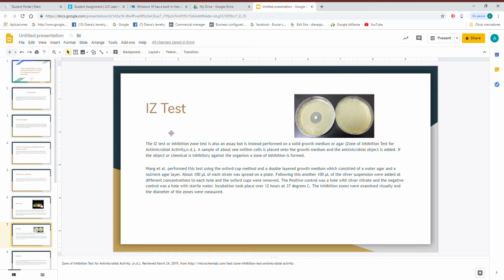So Wang et al. performed this test using the Oxford cup method and a double-layered growth medium, which consisted of water agar and a nutrient agar layer. So about 100 microliters of each strain was spread on the plate, followed by another 100 microliters of the silver suspension added at different concentrations to the hole, and the Oxford cups were removed. So Oxford cups are little cups that you place inside the growth medium and then just put whatever you're trying to put in there and then just yank them out, and whatever you're trying to get in there stays in there.